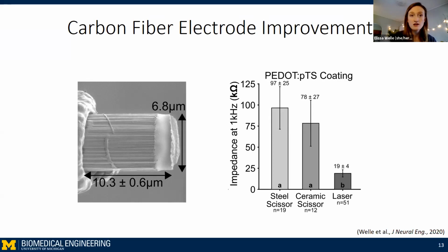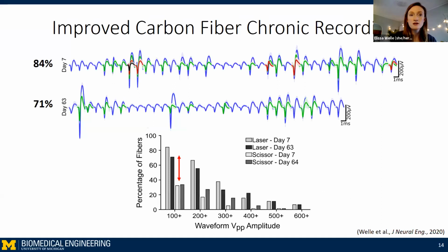So to test if these laser cut electrodes record from neurons, and hopefully from more neurons, we chronically implanted 45 electrodes in 4 rats over several months. After 7 days, 84% of the electrodes recorded units. And after 2 months, 71% still recorded units, both of which are much higher than the 30% we were seeing from the scissor cut electrodes. So we saw nearly a doubling in recording yield. But this is not just about quantity, it's also about quality. We were happy to see that the units recorded by the laser cut electrodes had amplitudes up to 600 microvolts peak to peak, which is quite high. And we saw that nearly 10% of our electrodes are recording an amplitude that high.